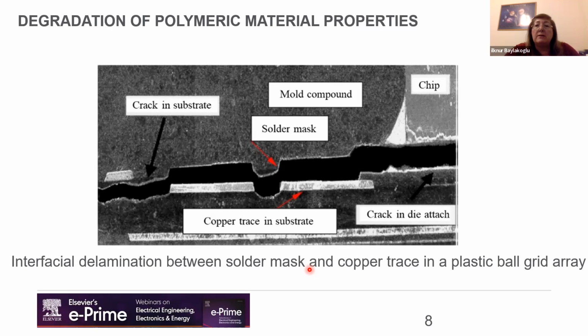So their hydrophilic parts can have some interaction between the polymer and, for example, adhesives applied to the interface of components. Adhesives degraded by moisture induce cracks in devices like here. Also these devices, especially during the reflow process, face very high temperatures. These cracks can happen. Under humid environments, some residual chemicals in adhesives can react with water molecules to form acids, which degrade interfacial adhesion. This type of delamination-induced crack occurs in different places, and it causes some stresses.